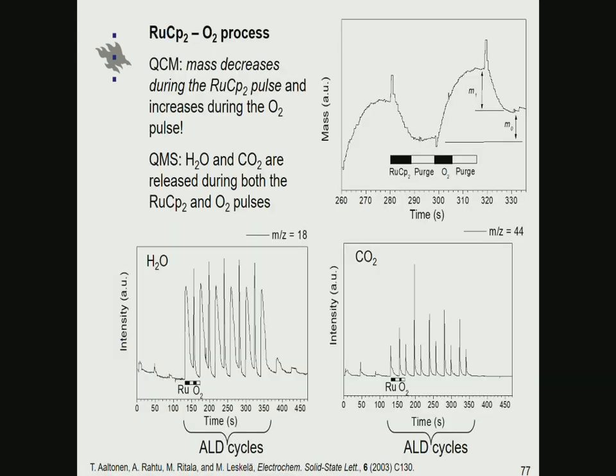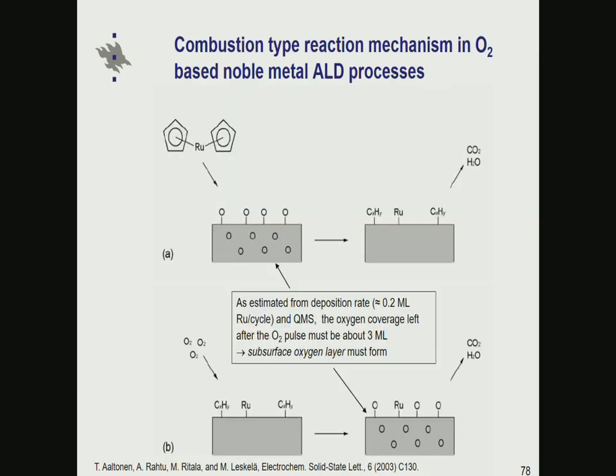So we have used quartz crystal microbalance and mass spectroscopy to study the chemistry there. Without going further into details, there is just one surprising thing I want to point out in this ruthenium process. So we have ruthenocene and O2. With the quartz crystal microbalance, we see that once we give a pulse of ruthenocene for growing the ruthenium film, we actually see mass coming down. And when we then give an oxygen pulse, we see mass going up, even if we use oxygen to remove the ligands from them. So what explains that is a mechanism which is shown here.